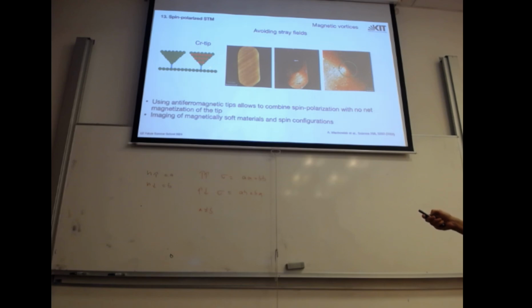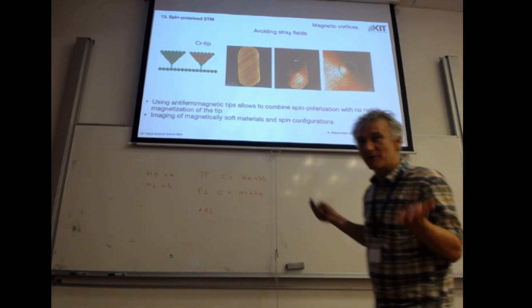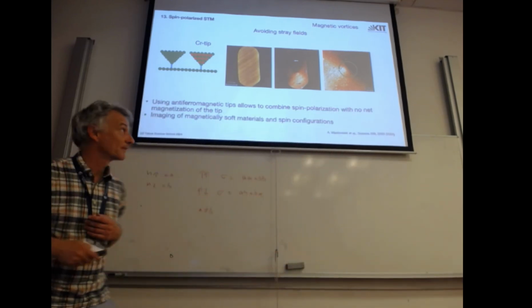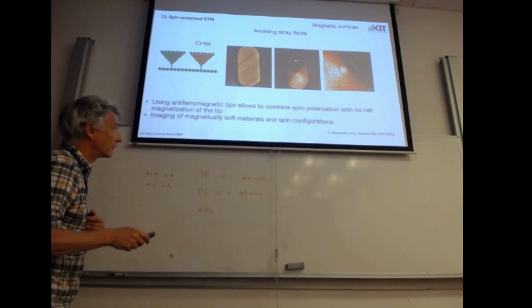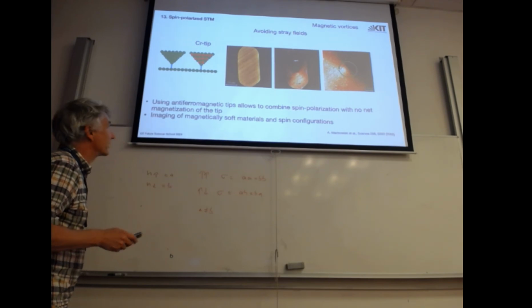So you can alternatively use an antiferromagnetic tip. Now this has no net magnetic moment, but the last atom, of course, has to be on either one sublattice or the other sublattice of the antiferromagnet, so it still polarizes the current. Basically, only the last atom counts. So in both of these images, the last atom is the green atom, so they give the same images in principle. And this is work from Roland Wiesendanger's team in 2002.